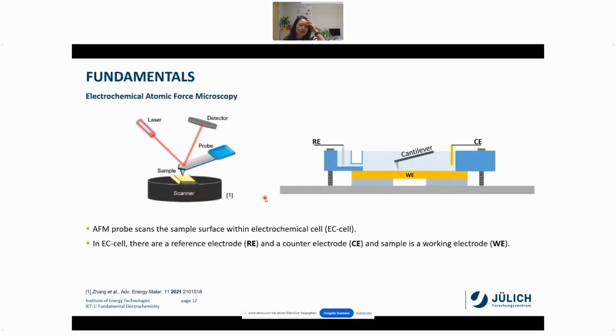Hello everyone, my name is Inhi Park. Now I would like to explain about AFM, atomic force microscopy, and how we use electrochemical atomic force microscopy. So this image shows typical AFM images. AFM probes scan the surface, and there are interactions between the AFM probe and sample, such as attraction and repulsion. Due to this interaction, the AFM probe bends toward the sample, or out of the sample. And this bending can be detected by the laser, which is reflected on the backside of the cantilever. Therefore, it's very important to locate the laser well on the probe and adjust the detector.